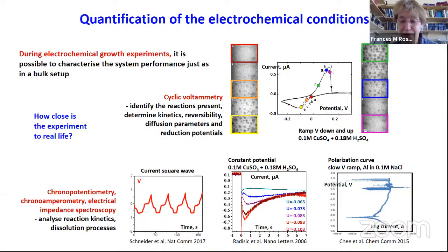For example, with copper sulfate, we have the correct nucleation and diffusion limited signal in the CV curves. We can do these polarization curves for corrosion, and they look pretty good. It's really important to compare with real life. And that's the basic level, is that you need to be seeing in the liquid cell what you would expect to see on the benchtop. And if not, then you have to think about what we should do to change it.